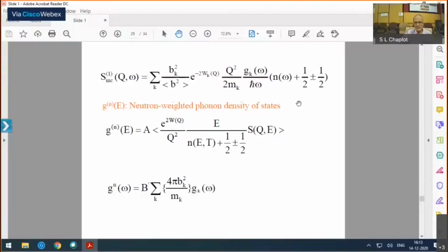Often the instrument scientist would know what kind of corrections are required, but as an experimentalist, you have to have some feel for how the corrections will depend on the various angles, the scattering angle for example, or the wave vectors. One of the ways we do this is by calibration. We may use a standard sample, often vanadium.